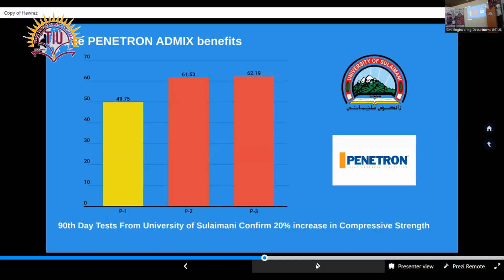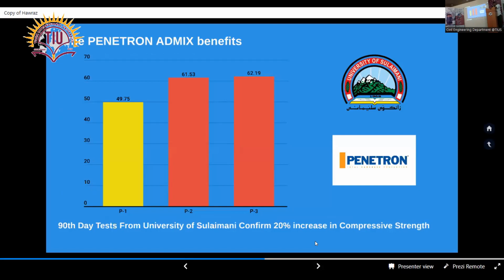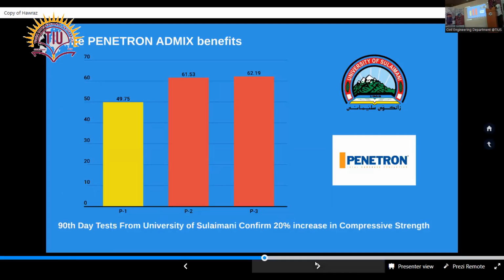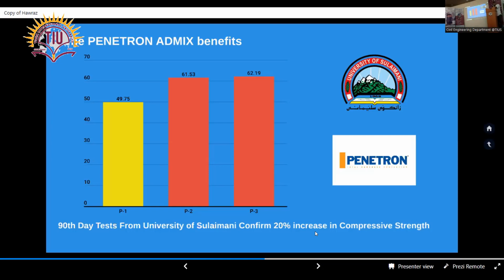Here we see from the chart the yellow bar, which is the control sample with no additive, has an average compressive strength of around 50 megapascal. The P2 and P3 samples, which are the samples of concrete containing Penetron admix, have around a 20% increase in compressive strength, giving an average value of around 60 megapascal. This is due to the fact that once inside the concrete, the Penetron admix starts to grow crystals, and all the capillaries and microcracks will be filled with calcium silicate crystals, and we will have a more compact and denser concrete, as is obvious from the 90 days test.